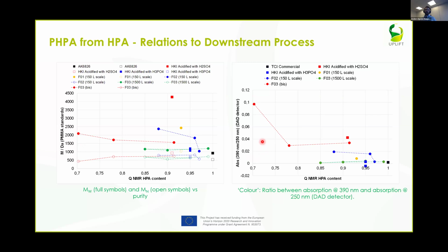And you can see on the right-hand side that in some cases, the absorbance curve on the y-axis indicates how much coloration you have in the systems. So you can see that when you go really far down in purity, there are compounds in there that would lead to a discoloration of the product. So it's not a free meal, but there are some possibilities in using less stringent purification processes, as you can also see from the green curve here, where increasing the purity from 85% up to almost 100% purity doesn't change much in terms of coloration, and similarly, the same study also doesn't change much in terms of molar mass for these systems.